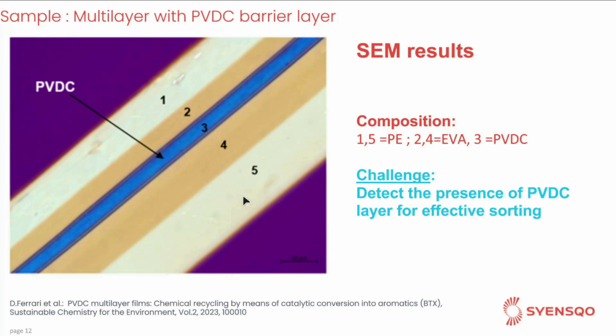Number 1 and 5 are made up of polyethylene. 2 and 4, the intermediate layers, are made of ethylene vinyl acetate copolymer. And the blue one, which is the inner layer, is PVDC, which provides the barrier properties to this multi-layer. Barrier properties means barrier to oxygen and at the same time to water vapor.